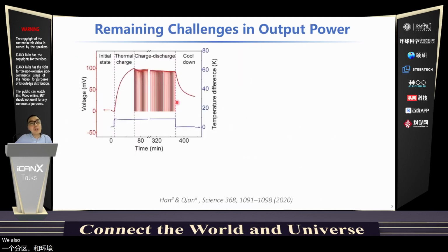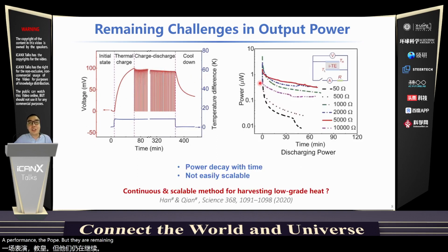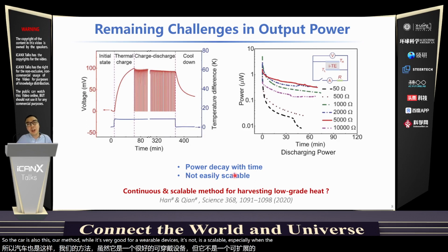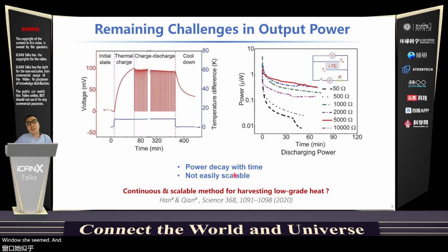We also do charge and discharge tests of hundreds of rounds, and we basically do not observe obvious performance decay. But there are remaining challenges. One is that the power decays with time, and that is because the thermal diffusion is a physical effect. So the current is capacitive. Also, this method, while it's very good for wearable devices, is not easily scalable, especially when the heat sink and the heat source are far away.